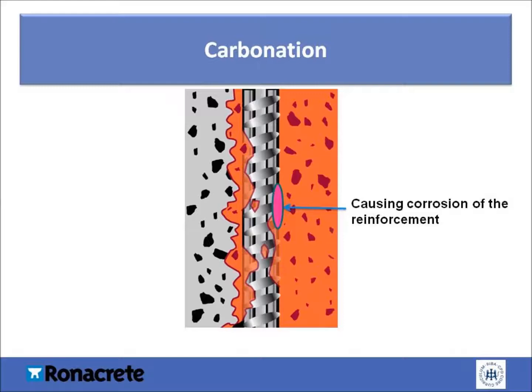Carbonation is generally a slow process. In low-quality concrete, it's been estimated that carbonation will proceed at a rate of up to 1 mm per year. But the rate can be much slower in concrete designed with a low water-to-cement ratio and high cement content. Carbonation-induced corrosion is often worse when areas of building facades are exposed to rainfall, shaded from sunlight, and have low concrete cover over the reinforcing steel.